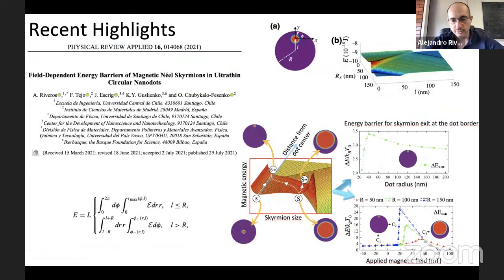In another work also published this year, we have studied the energy barrier of skyrmions in ultra-thin circular nanodots by theoretical calculation, by calculating the magnetic energy of the skyrmion as a function of the skyrmion core and as a function of deviation length.